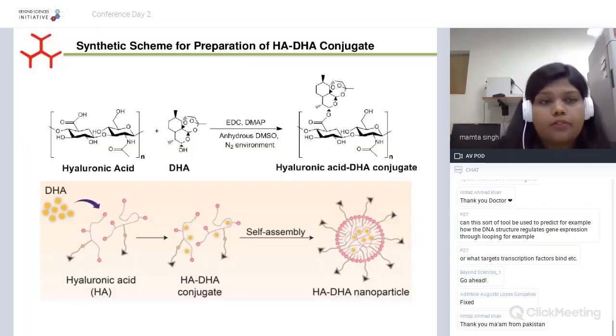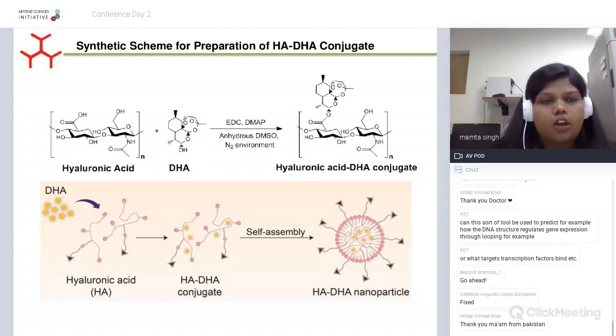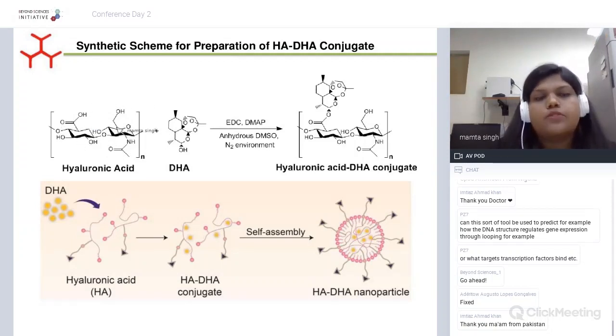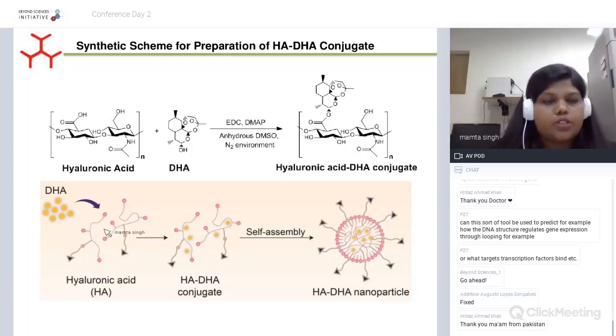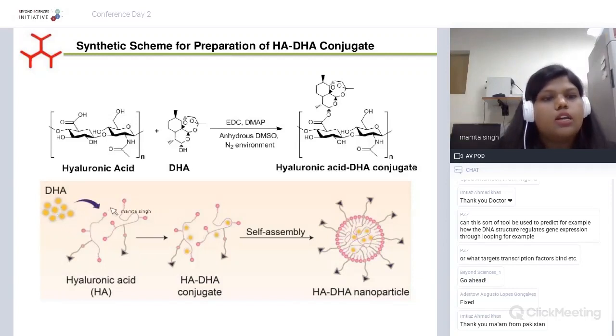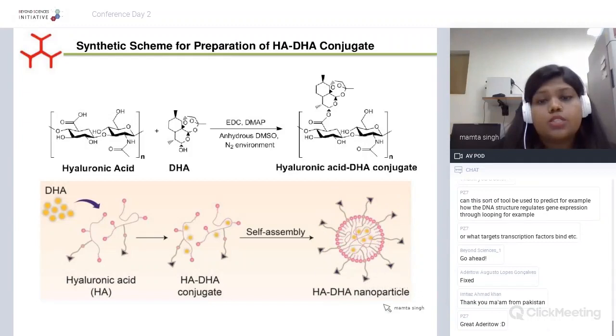To address these two problems, we used the hyaluronic acid-based platform for conjugating DHA for anti-cancer purposes. DHA, which is hydrophobic, and hyaluronic acid were directly coupled using an esterification reaction to synthesize the conjugate. In the pictorial representation, the hydrophobic DHA is conjugated to the hydrophilic HA moiety, and when kept in aqueous solution they are anticipated to self-assemble into nanoparticles with enhanced permeation and retention effect over cancerous cell lines.